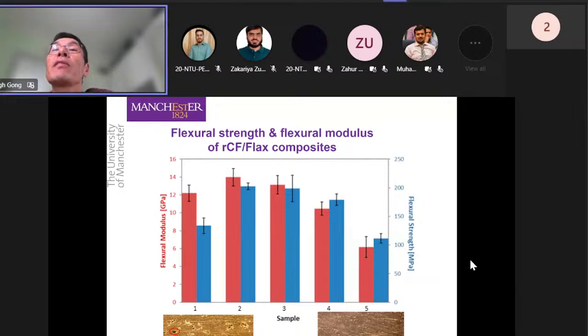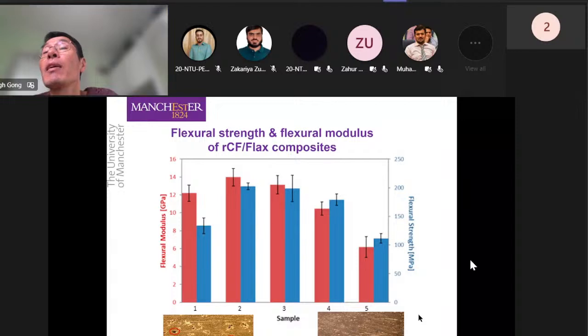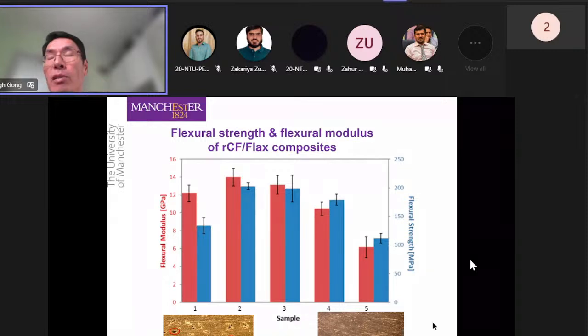Now, if it's 100% flax, obviously flax fiber is not as good as carbon fiber. And you can see also there seems to be a lot of void within the composite itself, which obviously for composite materials, voids are particularly negative for the performance. While the right-hand side is a 25% mixing, 25% of flax, 75% of carbon fibers. So you can see the void content is much reduced. There are not really any visible voids. But as the carbon fiber content increases, the problem of fiber entanglement and clustering becomes more serious. And that's when the composite material performance starts to decrease.